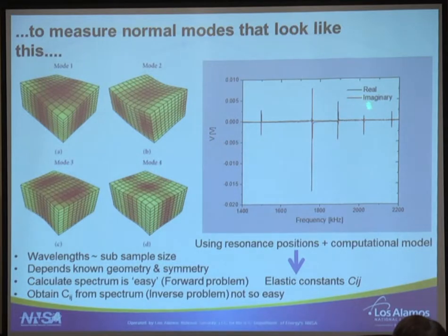You measure the voltage, the real and imaginary part, as a function of frequency. And each one of these peaks depends on the elastic constants of the material. Each one of these peaks depends on one of these modes. These are simulations of displacement of a parallelepiped, and this is the first mode, this is the second mode. So usually the first mode is a shear mode, so you have something that goes like this, and then you have a mixture of different elastic modes in each one of these frequencies.